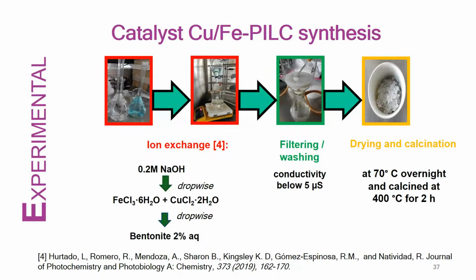So we prepare these solutions with these salts, and we add this to change the pH, and add it dropwise to the bentonite, then filter and wash. And to be honest, this washing is one of the less sustainable stages of the preparation of this catalyst, because it takes a lot of water. Why? Because the conductivity must be below 5 microsiemens. So it takes a lot of water here. And then is drying and calcination under these conditions. Here is the reference of this process.